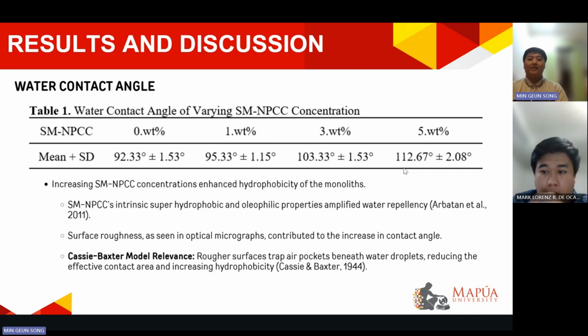The water contact angle measurements for PLA SM-NPCC monoliths show a positive trend, increasing with higher SM-NPCC content. This trend can be attributed to the changes in surface morphology observed in the optical micrographs, which revealed a progressive increase in surface roughness with the addition of SM-NPCC. Additionally, the inherently superhydrophobic and oleophilic nature of SM-NPCC further contributes to the overall water-repellent behavior of the monolith.